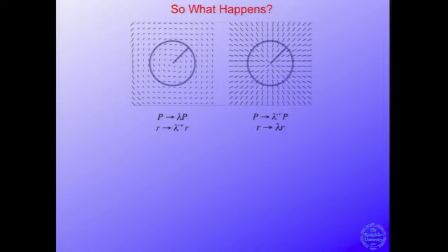If you turn the directors around into the radial case, you get the opposite senses. You get an expanding perimeter and a shrinking radius. And notice, of course, that this is all completely symmetric, so I could have taken any circle in the material. At all length scales, it's the same thing.